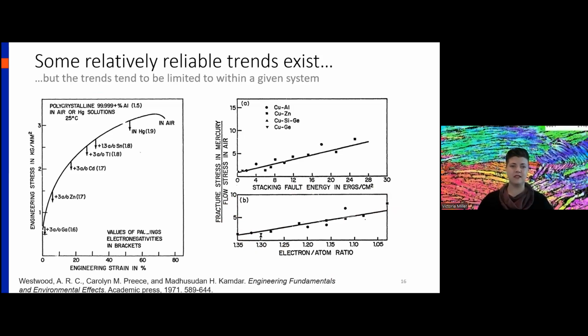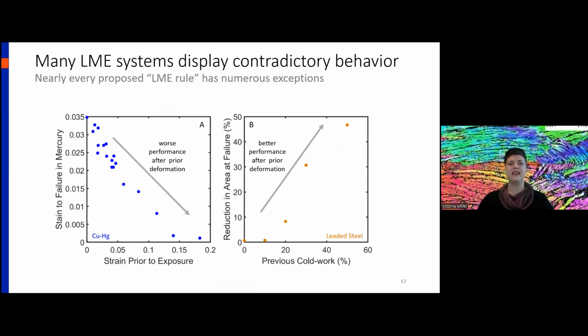If you start digging deeper into the literature, you start seeing contradictions. So if we look at the sensitivity of liquid metal embrittlement to prior strain, on the x-axis here, we have some measure of prior strain, and on the y-axis, we have some measure of strain to failure. In the copper mercury system, you get worse performance after prior deformation. Whereas in this system, leaded steel, you actually get better performance, increasing strain to failure after prior deformation.